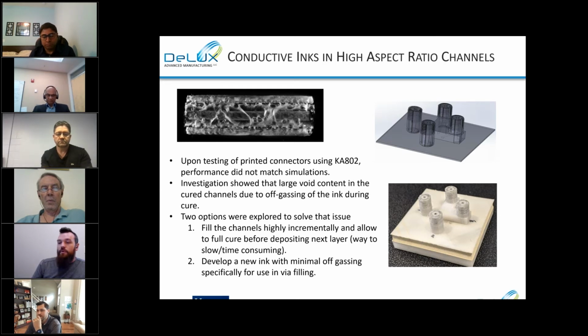DuPont came to us, asked us what we liked and didn't like about their inks, and we went through an iterative process with them, and they generated KA802. It's an excellent ink if you're printing onto surfaces, doing complex features, small features, high conductivity, and it's a fantastic ink for basically every application we've come across except for this one, which is to fill these long high aspect ratio channels. There is some off-gassing that occurs, and you can see this is a CT scan of one of our printed through-line connectors, and you see a large void content.